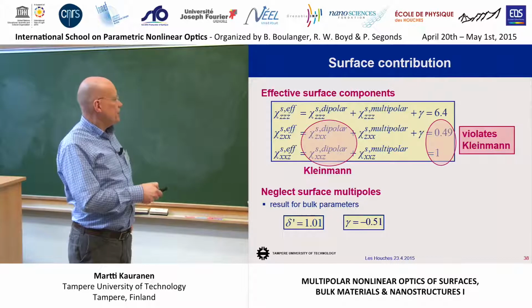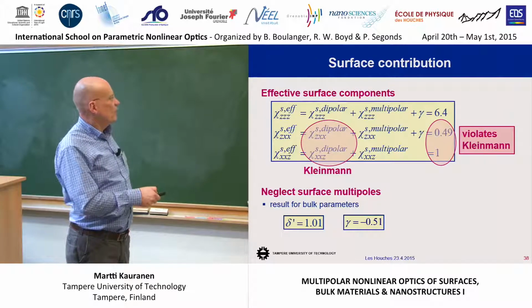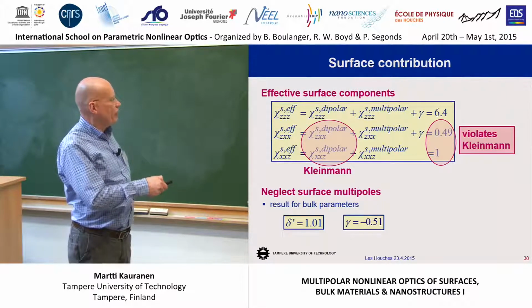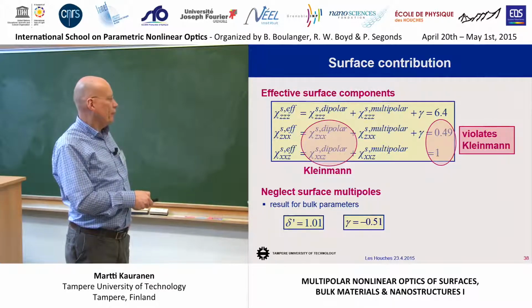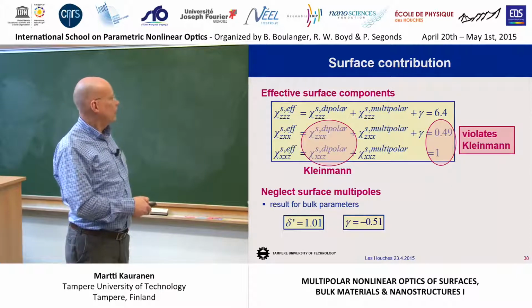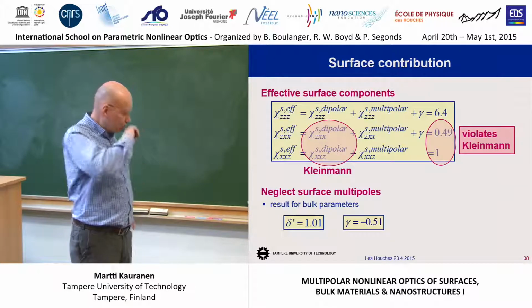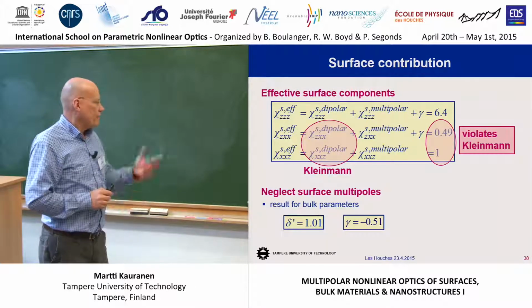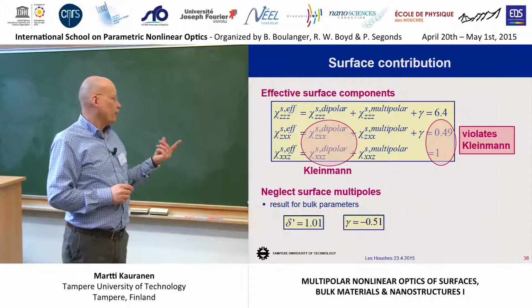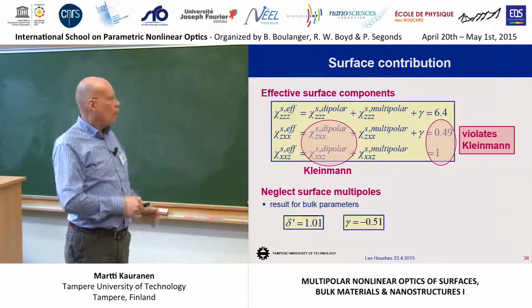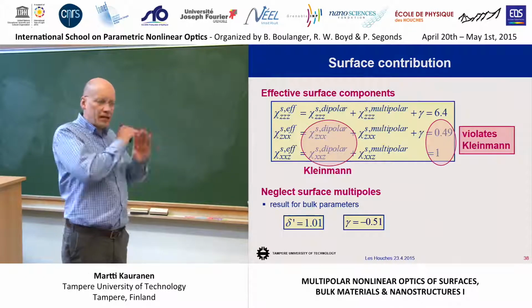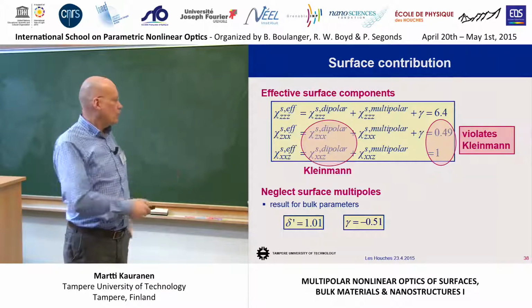And then in these units, if we assume that we can explain this deviation by the presence of this bulk parameter gamma in the effective surface response, we get that gamma would be about 1/2. And then delta prime, which is not on this slide, it was from the previous slide, was about 1, okay? So now we have estimates for the two bulk parameters. One measured through the surface response, because that's the only thing we can do. One measured directly.